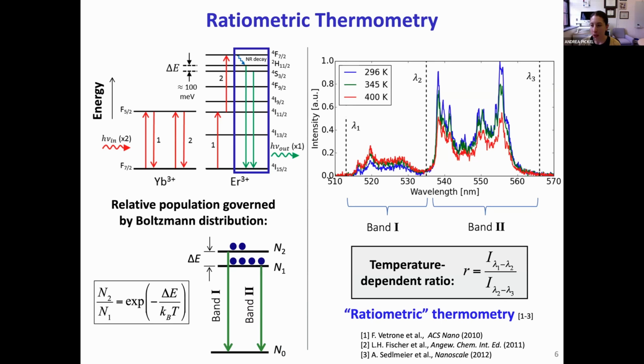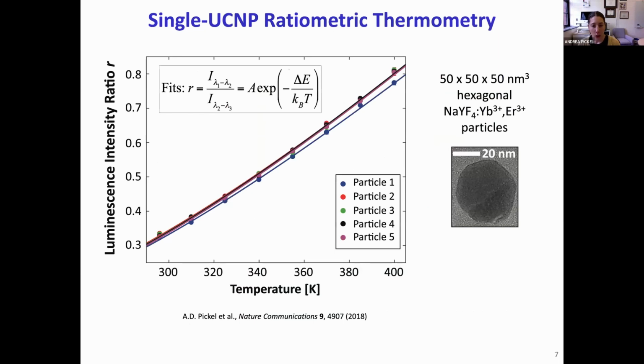And while it's been used fairly commonly for ensembles or large groups of these nanoparticles, back when I started working with them during my PhD, there had been very few single particle measurements and certainly none using particles 50 nanometers or smaller. So a large part of my PhD was demonstrating the first ratiometric thermometry measurements using individual UCNPs, 50 nanometers and smaller. And this plot shows the luminescence intensity ratio as a function of temperature for 5 individual UCNPs. The temperature sensitivity of the technique is quite good, and there's also excellent particle-to-particle uniformity, as you can see from the nearly overlapping calibration curves for these 5 different particles.